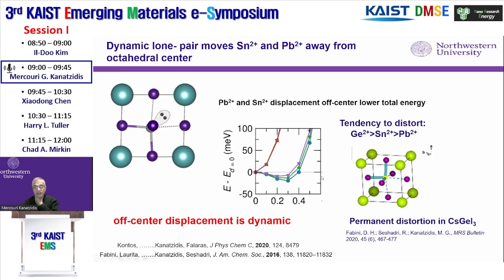That means that there is a natural thermodynamic tendency for the atom to go off-center in the octahedron, because the octahedron is totally symmetric and it doesn't allow any room for the lone pair. So these atoms are pushing to get off-center, but the structure is pushing them back into the center of the octahedron. And so there is a big competition between these two effects. In fact, theory also predicts that when you move the atom away from the center and you calculate the energy of the system, the energy goes down before you move it too far from the center, and then of course it goes up. So there's a minimum in the energy in an off-center position, which is very interesting.